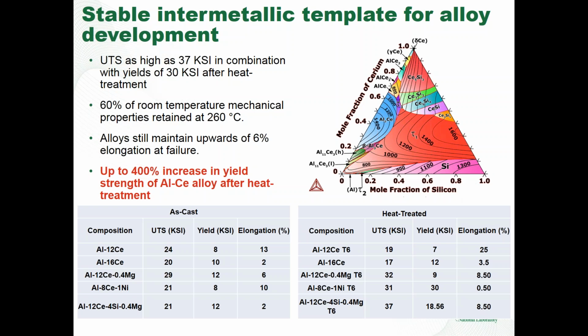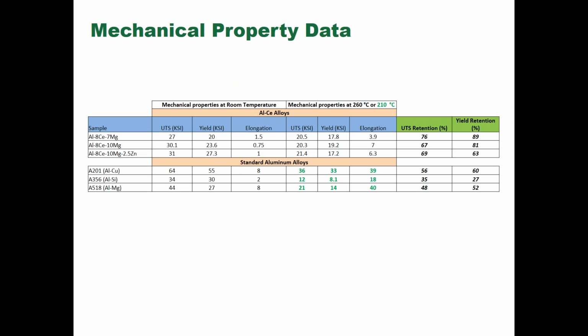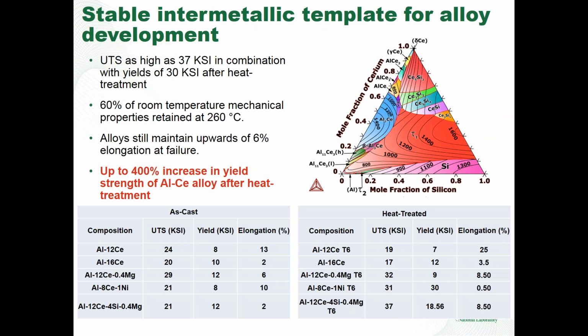So there, as I think I said, we did somewhere between 20 and 30 different compositions of alloys using a lot of different alloying elements, and some of these materials responded well to heat treat, and some didn't. I'm going to go back one slide because I will add that these are as-cast properties for the alloy at both room and high temperature for the aluminum-cerium alloys. For the conventional alloys, these are all heat-treated properties. So we're getting very, very good mechanical properties actually without needing to heat treat the alloy.